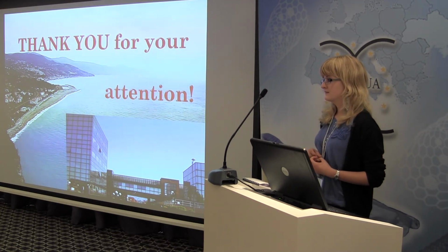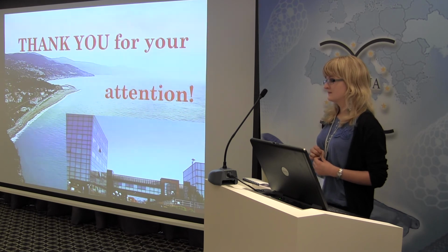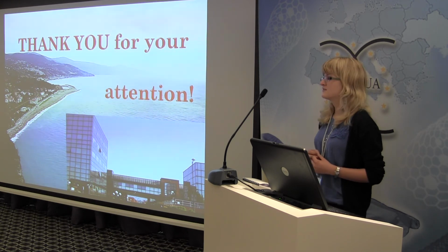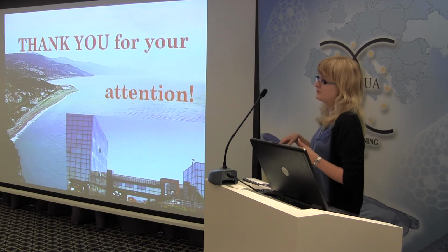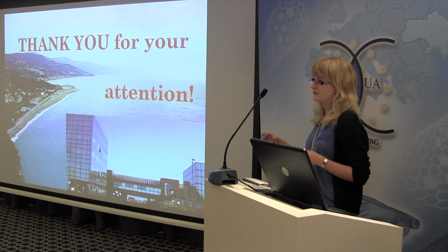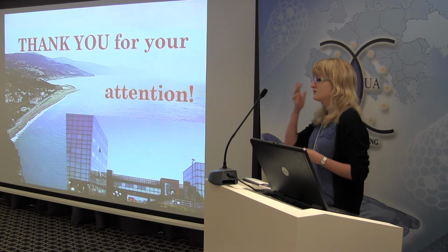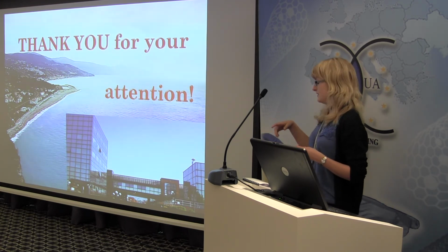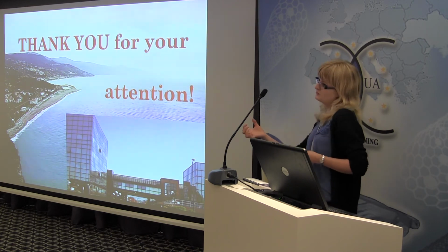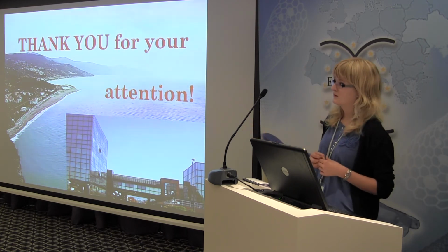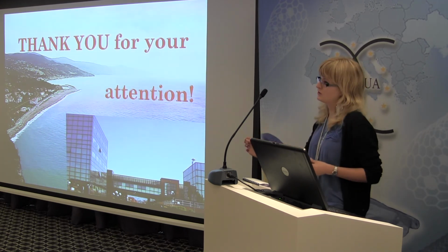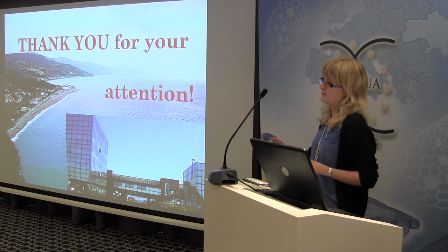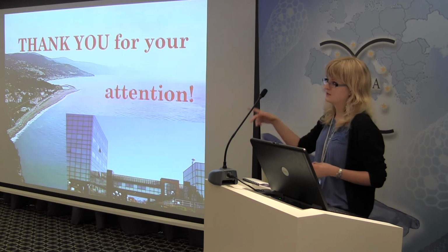What about the temperature dependence of the period? All the measurements that I presented here were done at the same temperature, because you're right that the period depends on the temperature, and the closer you are to the smectic-nematic transition, the smaller the period you will observe. I mean, in the same place, you will observe a smaller period when you increase the temperature and get closer to the smectic-nematic transition.